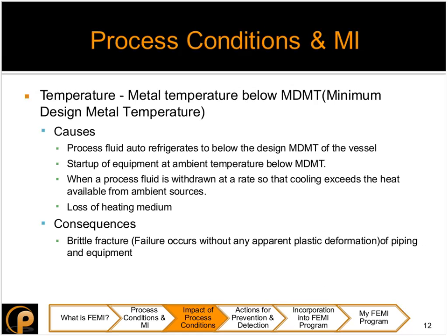Or when a process fluid is withdrawn at such a large rate that the cooling exceeds the heat available from the ambient sources. It can also happen when you have a loss of a heating medium within your tank or your pressure vessel. As a consequence of the equipment operating below the MDMT, brittle fracture of the equipment can happen. Brittle fracture is always sudden and it occurs without any apparent plastic deformation of piping or equipment.